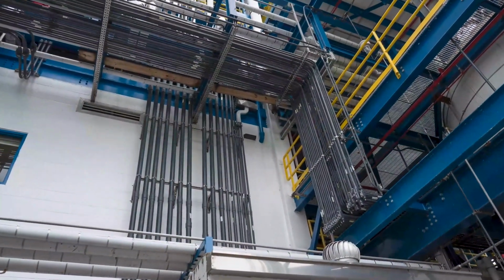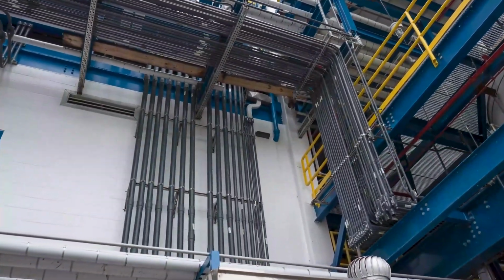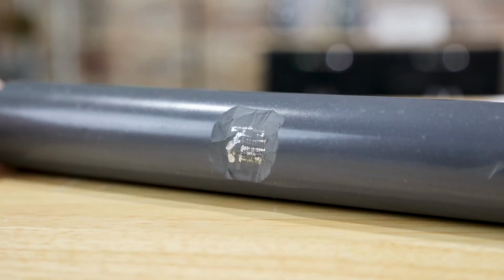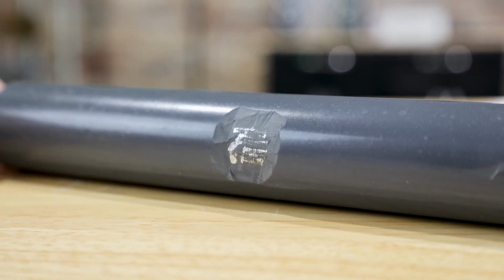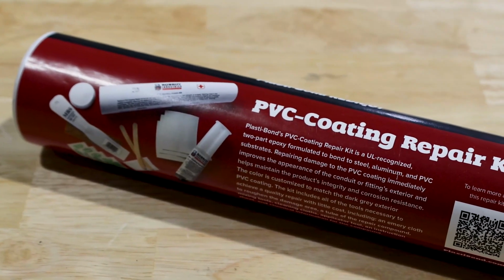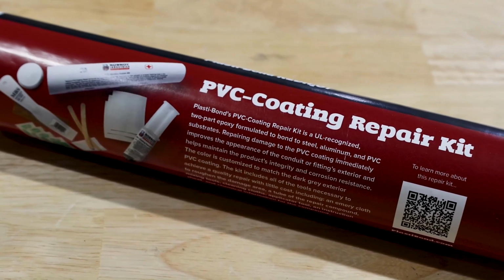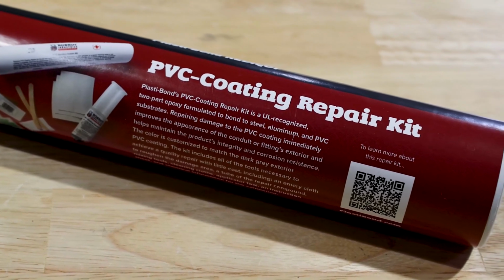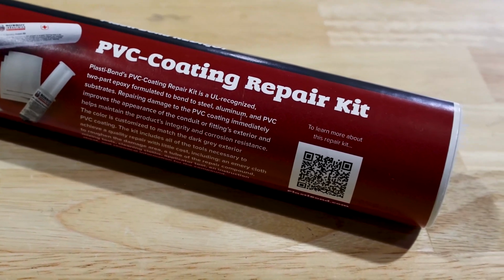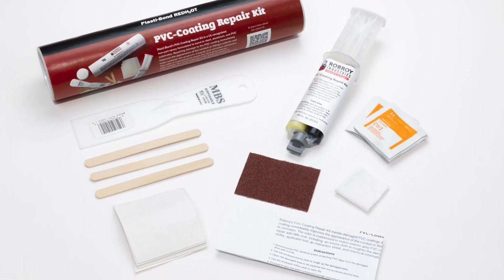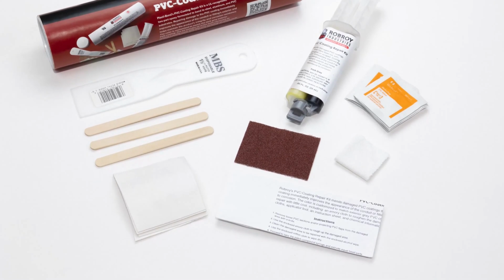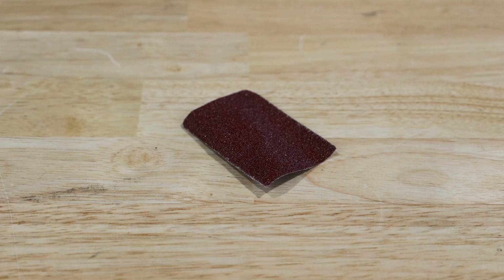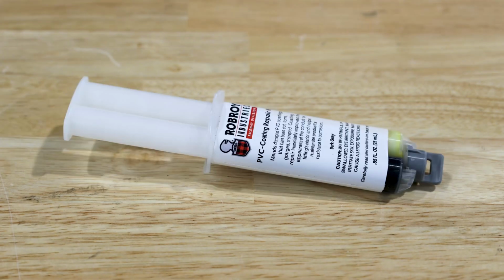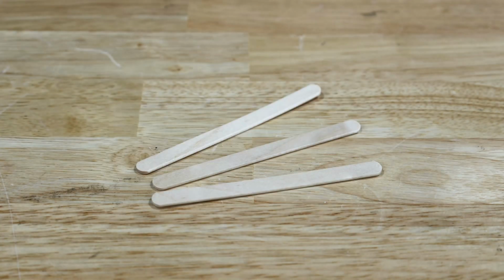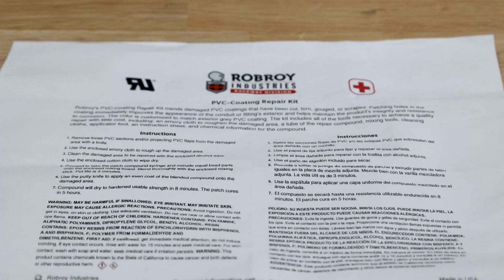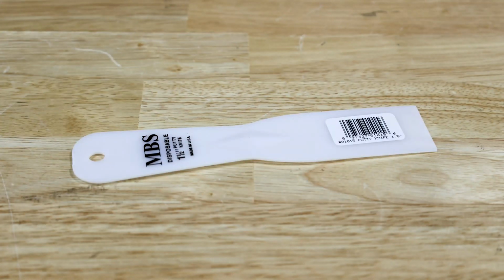PVC touch-up compound, however, is not formulated or intended to bind to the metal substrate when damage penetrates the coating and exposes the metal substrate. For these cases, a PVC coating repair kit was developed using a custom-formulated, UL-recognized, two-part epoxy capable of bonding to both polyvinyl chloride and steel or aluminum substrates. The repair kit includes all tools needed to prepare a small surface prior to applying the epoxy patch. This includes an emery cloth to prepare the surface of the damaged area, the epoxy solution, cleaning cloths, mixing tools, mixing board, instruction sheet and chemical information, and an applicator tool for the compound.